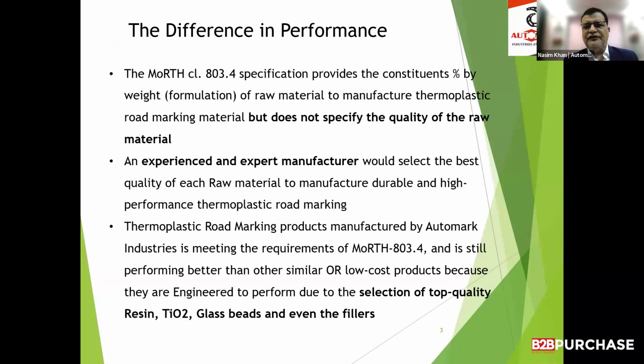The formulation of thermoplastic road marking is given in the MoRTH specification. The Ministry of Road Transport specification guidelines 803.4 clearly define how you make thermoplastic road marking material. What should be the constituent percentage by weight? It says that 18% should be resin, 10% should be titanium dioxide, and 30% should be intermix glass bead, and the rest 42% should be fillers.